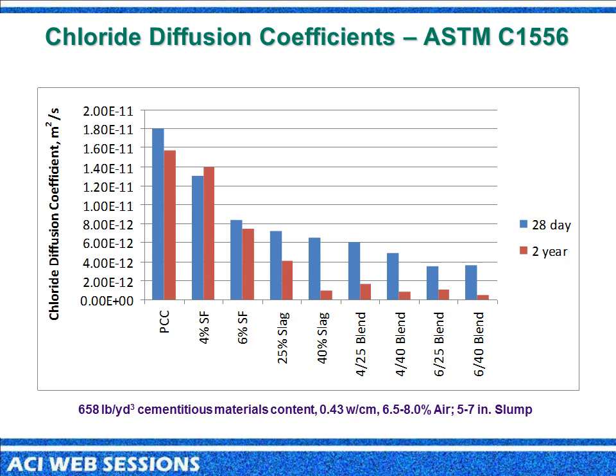But what we have seen is that when we look at the chloride diffusions using the ASTM C1556, we can see what we would expect, where we would see the diffusion coefficient is being lowered over time. Now, you notice we only have 28-day and 2-year data. You're probably saying, well, we know you had to do this for 1 year. What we found very interesting is that the concrete specimens were so dense that we could not actually have any permeability occur at 1 year.